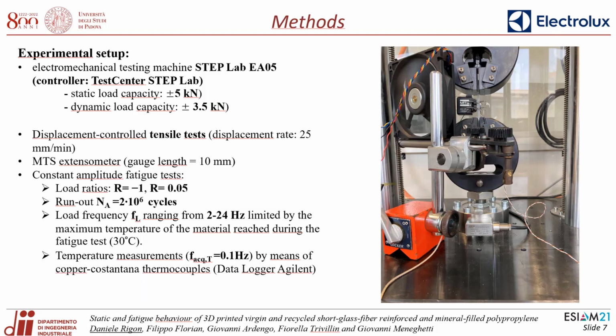The experimental setup consisted of an electromechanical testing machine, StepLab EA05, with a StepLab test center controller. The static load capacity of this machine is plus/minus 5 kilonewtons, and the dynamic load capacity is limited to plus/minus 3.5 kilonewtons. The tensile tests were carried out in displacement control mode with a displacement rate equal to 25 mm per minute.